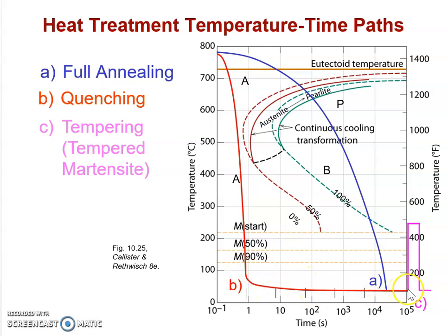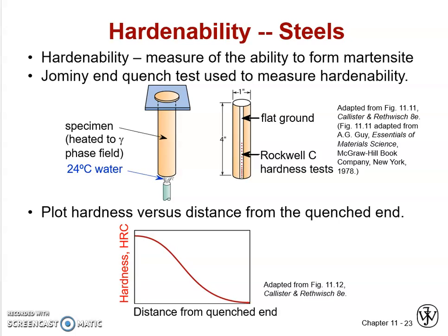Okay, and then you heat it back, around 400 to 500, and you hold it for some time, and then you cool it. Then you will get tempering. Okay, that is the tempering process. You get tempered martensite.